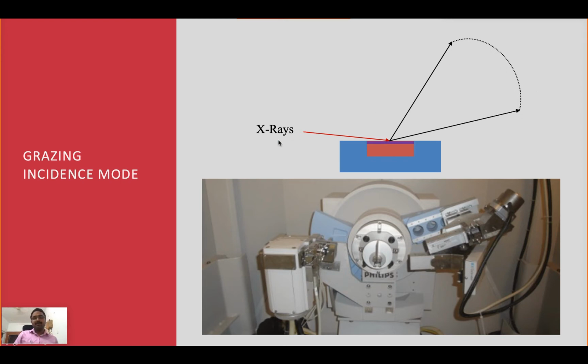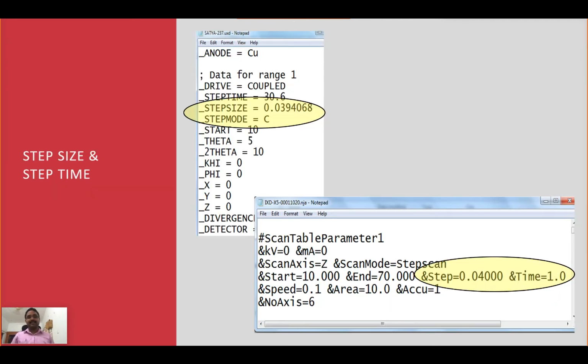So in this mode, if you take your X-ray diffraction data, there is a good chance that the diffraction will take place from your sample, not from the substrate. So to avoid the substrate effect on your sample, this grazing incidence mode is important. Sometimes it is called GI mode. Technically it is called GI mode. So next time you are going to take data, please inquire about this mode and use it for your thin film sample. This is another example of a precaution in how to take your X-ray data.